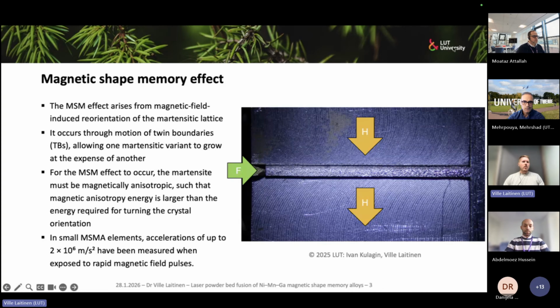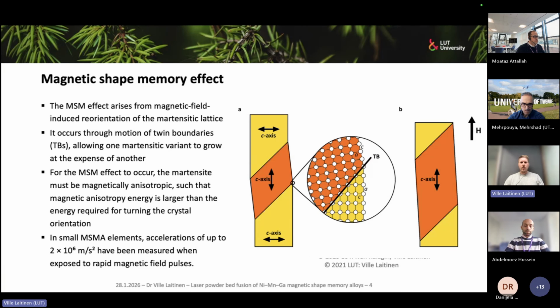Okay, here. So the magnetic shape memory effect: you can see on this right side video, that's actually a nickel manganese gallium single crystal in an electromagnet. And where you have this marking F with the arrow, that's spring-loaded pressure. So by an external magnetic field, we effectively elongate this element. And then once the field is removed, by the spring force we bring the element back to its original configuration. And how this effect actually happens is that we have nickel manganese gallium martensite.